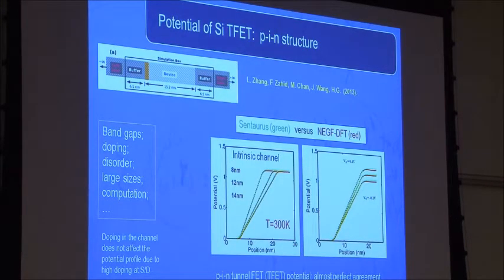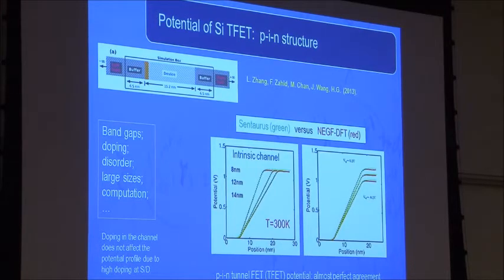This one is not very large, actually maybe 800 atoms or something in this region, but nevertheless, if you put the two curves together, they are quite reasonable. They agree. There are no adjustable parameters in our calculation. We sent these curves to them, and you see that at non-equilibrium, we differ a little bit. We found that in Sentaurus, they use something called a floating boundary condition to solve the Poisson equation, and we use a fixed boundary condition. That was the little difference, and I believe the fixed boundary condition is actually more physical.